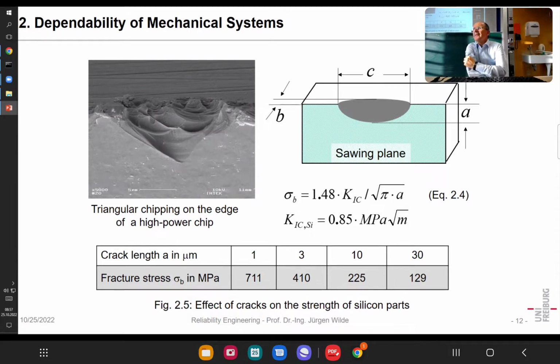But the correct answer would be, it depends on the crack length. Here, for silicon, you can say you have a fracture toughness. You find different values. Also, the crystal direction has an influence. So here we have taken 0.85 megapascal square root of meter. And now we take that formula, and here we take for the Q factor 1.48. Somewhere in between 0.7 and 2.5.